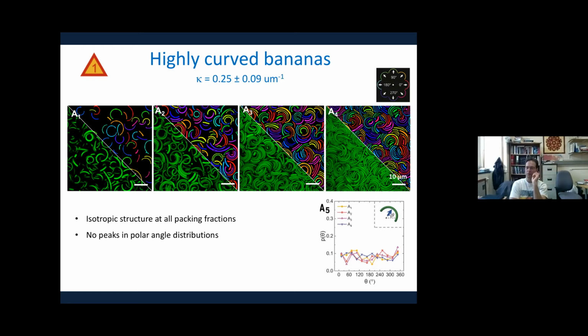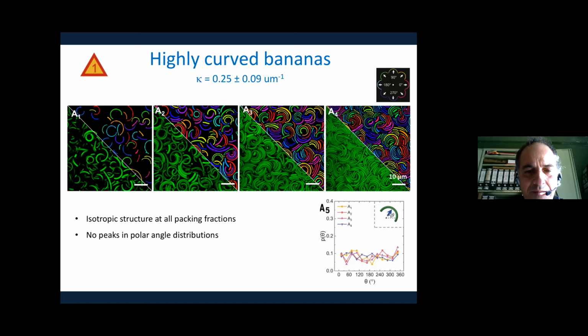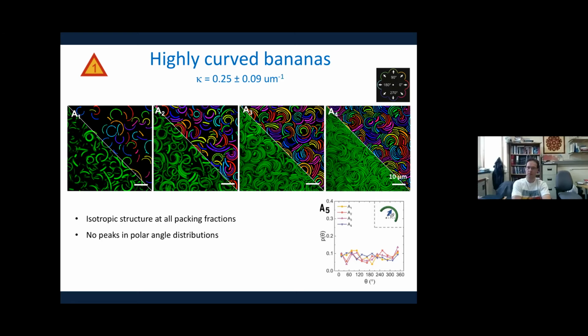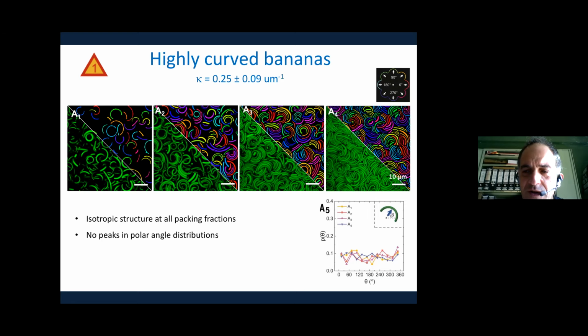Oh, I see. That's interesting. Yeah. And so the smectic phase is a lot more stable once you have these literal boomerangs compared to the curved bananas. Curved rods don't form the smectics that easily. So there is a bit of difference between a boomerang and a banana. Now we are getting into the realm of these very subtle differences that can have very remarkable consequences, like the difference between ellipsoids and spherocylinders: spherocylinders can form a smectic phase and ellipsoids can't. That sort of subtle detail may be subtle but is nevertheless quite important.